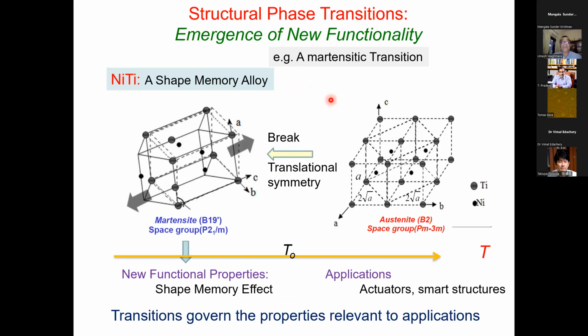martensitic phase transformation. And this is in a very prototypical material called nickel titanium. At high temperature, this material occurs in a cesium chloride-like structure where nickel is on the cubic lattice and titanium is at the center of that lattice. But as you lower the temperature, it reduces the symmetry of this lattice by deformation, which involves significant changes in the lattice constants, and also the internal positions of atoms, which break translational symmetry. And as a result, you get this low temperature phase called martensitic phase, which has a new functionality like shape memory effect. These effects are relevant to use of these materials in actuators, smart structures, and so on.